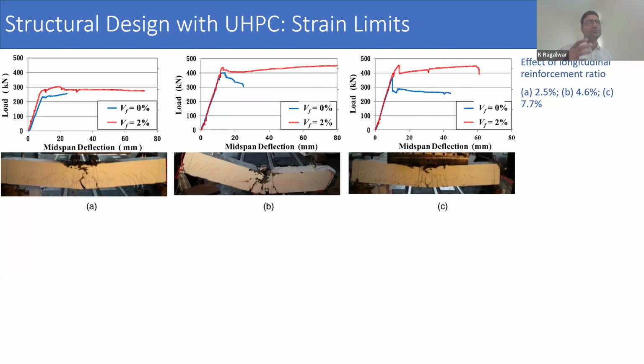That's the reason I'm showing this slide: to show you that based on the reinforcement and based on the fiber distribution, because we can see there are two different fiber distributions. The blue color has 0 fibers, whereas the red plot shows 2% fiber. So based on the fiber amount and the reinforcement amount, the behavior of the beam under flexure is very different. And to capture that uncertainty, they introduced this capping of behavior of the tensile block at strain localization and applied a factor to it.